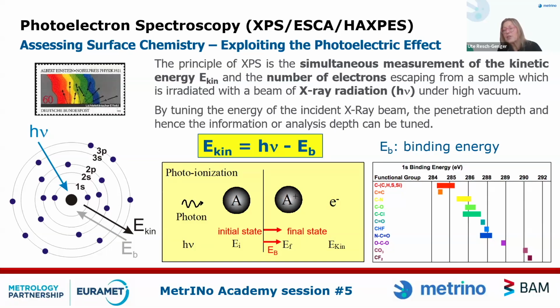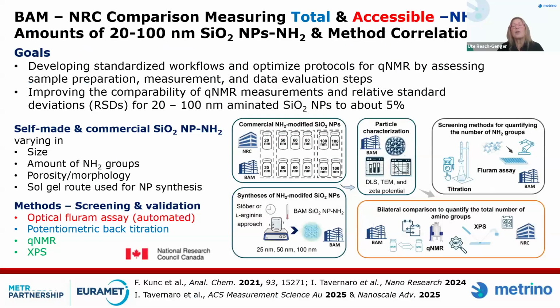photoionization, the different binding energies of different carbon species, for example, to give you an idea what you also can learn from XPS. And it's broadly used. So, what was now relevant for us were these 4 methods to do really a comparison with another group using different silica particles from commercial sources, varying in size, varying in preparation method, varying in morphology, amount of amine functionalities, just to get an idea. And this is one of the key messages of this presentation.